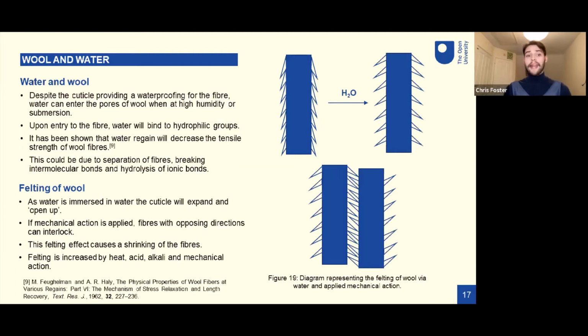Now, when water enters the fibre, it can actually bind to hydrophilic groups. So that's those groups that are attracted to water inside the fibre. And it has been shown that as the moisture content of the fibre increases, the actual tensile strength will decrease, so the wool will get weaker.